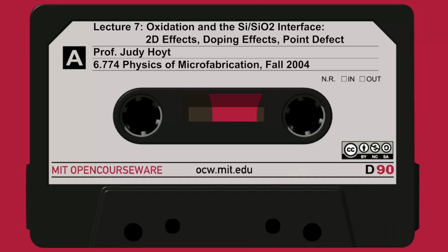Because it has to push it out, and it's constrained. So this mechanical work actually can modify the energy, the activation energy of the process, the amount of energy that it takes to do that process at a given temperature. So what we write is the EA, the activation energy for the surface reaction rate under the stress case, when we're oxidizing in a curved surface.